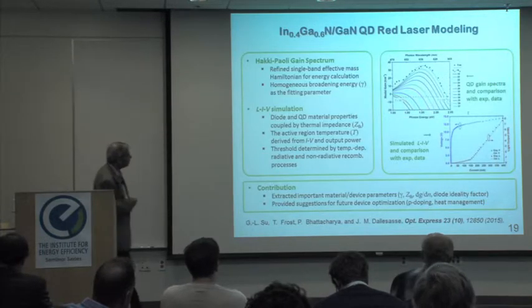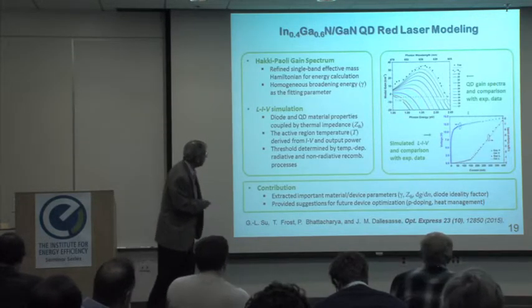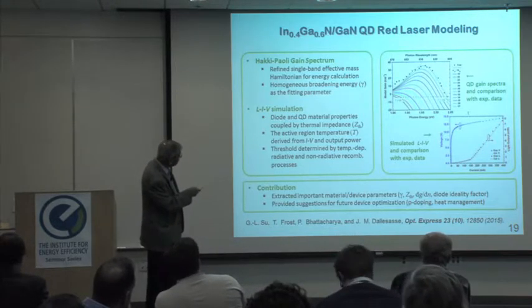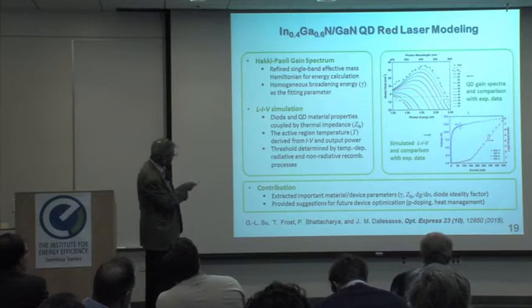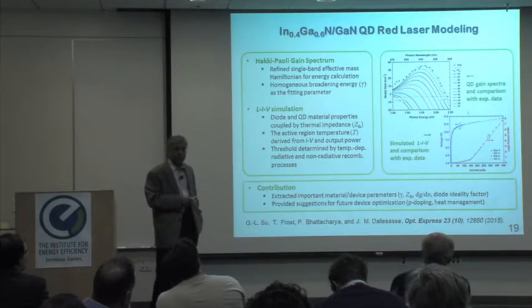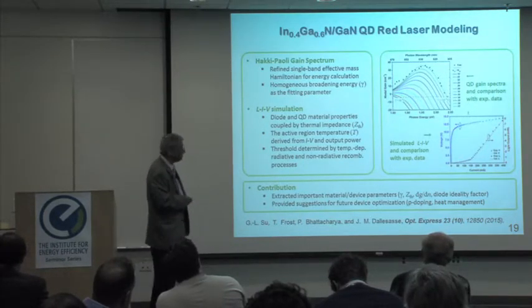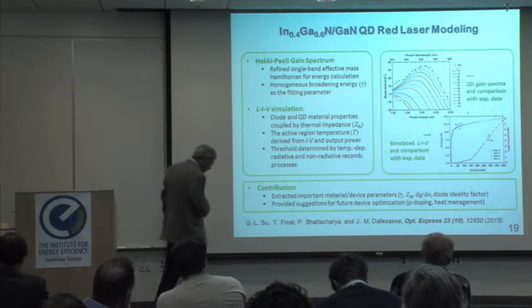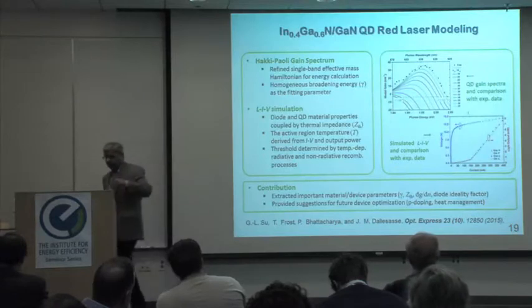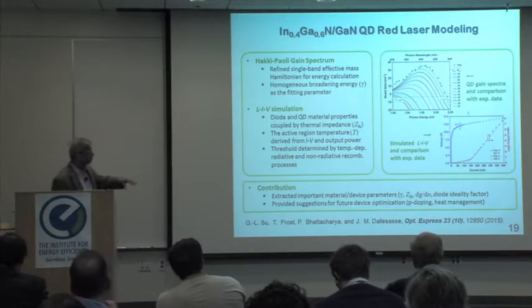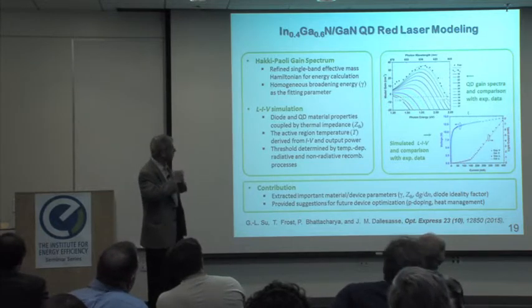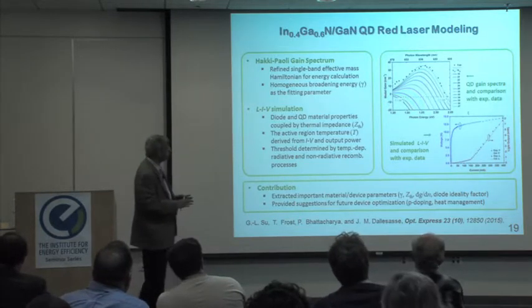And here you see they have tried to fit our measured gain spectra, again as a function of temperature, and you can see they can fit our measured gain at about 120 degrees centigrade. So the devices are really heating up, and that is one reason why their lifetime, and I don't mean carrier lifetime, I mean their lifetime on this planet, is small. So we just make all the measurements we can till they die.